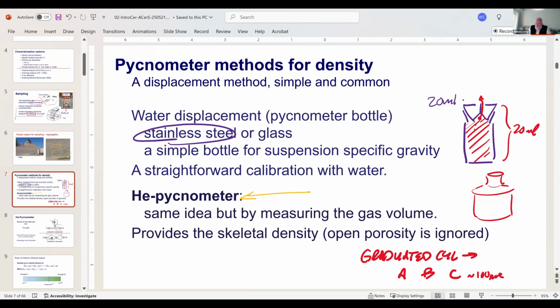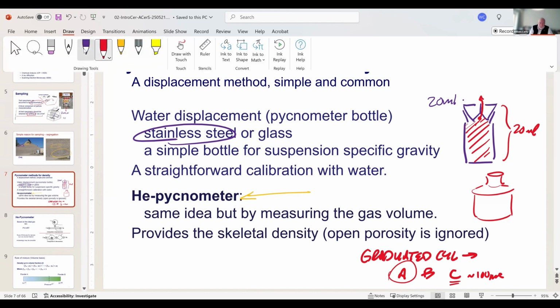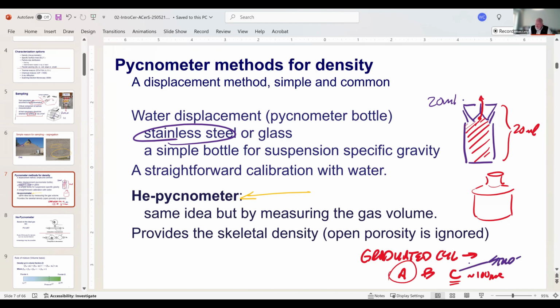And then B is industrial grade, and A is research grade. If you're doing this type of thing for measuring density, get A. They cost more, but this is analytical grade. So you'll see them written right on the cylinder. He used a C grade when he did it, a student grade, and that student grade turns out to not be 100 milliliters. What he thought was 100 milliliters was actually like 104 milliliters, something like this. So they call it student grade.